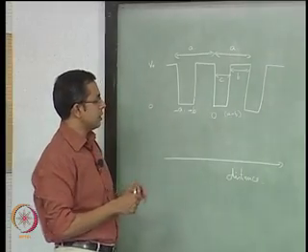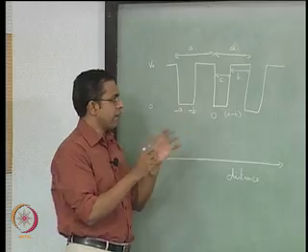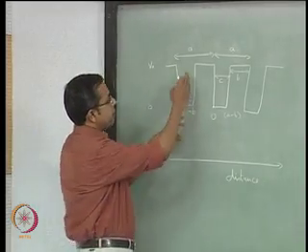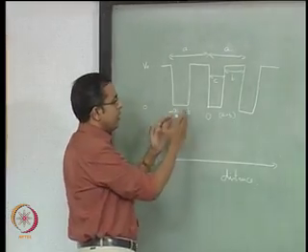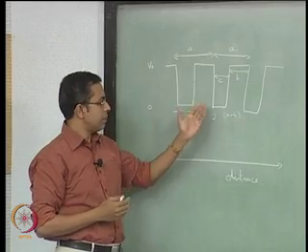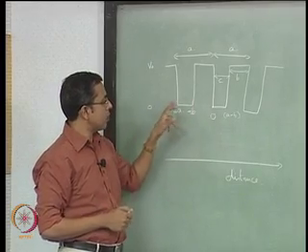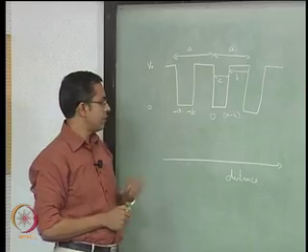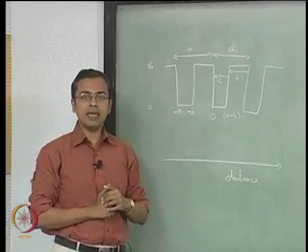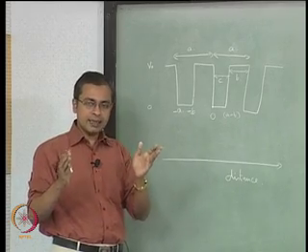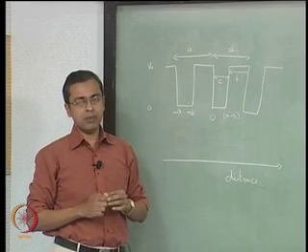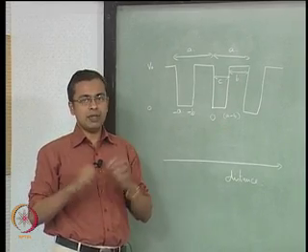That is how we would get two equations, and we will find that there are certain constants that we will need to figure out. Additionally, we have periodicity in this lattice, and there is a way to represent periodicity in terms of the wave function. That periodicity will ensure that we can compare two other locations in the system which are periodic, and for those two locations we again say that the value of the function has to be the same and the derivative has to be the same.